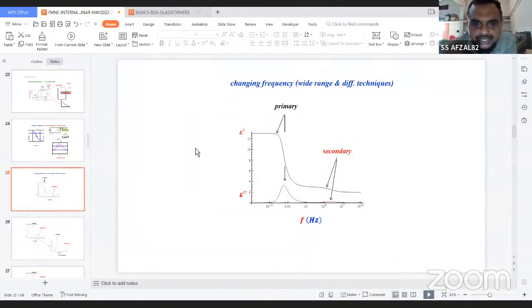So what happens is there is a change in the dielectric relaxation. During a dielectric relaxation, the real part and imaginary part of the dielectric constant change like this. This is a step-like change which corresponds to the primary relaxation, which is due to the cooperative motion of the molecules, which are dipoles. The secondary relaxation corresponds to the change in the dielectric constant due to the local motion of the molecules. Accordingly, there will be a peak in the imaginary part of the dielectric constant, which corresponds to dielectric loss. So from the dielectric loss peak, we can understand the frequency or the time constant of the relaxation.